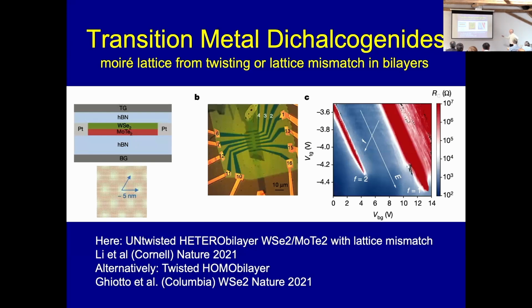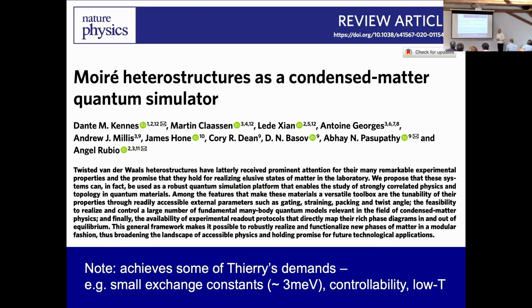And what you see is regions of very high resistance in red, which you can characterize as insulators, and regions of much lower resistance in blue, which you can characterize as metals. And by varying these two gates, you can actually move from one insulator to another one. As you will see in the following, what these gates do is vary both the filling of the system, so you can control the electron density, but you can also control the band structure. So there is something called the displacement field, which is the difference between the back gate, the bottom gate, and the top gate, which really controls the bandwidth and also some important parameters that I will describe in a couple of slides. So to a large extent, this system, if you want to push it a little bit, realizes some sort of quantum simulator of our dear quantum many-body problems.